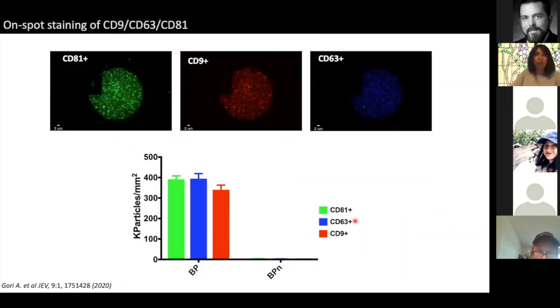Then we also confirmed the EV nature of the captured vesicles. So we performed an on-spot staining of the chip using the anti-CD9, CD63, and CD81 antibodies, fluorescently labeled in 3 different colors and imaged in 3 different fluorescent channels by the instrument. These are the CD81 positive vesicles captured on the spot, the CD9 positive vesicles, and the CD63 positive vesicles captured on the spot. Again, you can see that the background around the spot is very clean, and also that the capture by the negative control is basically not detectable.